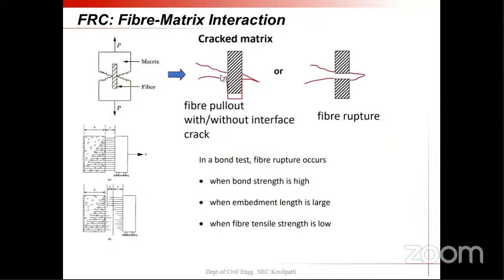So we are not going to apply 1600, because the fiber's tensile strength may vary from 1600, 1700 MPa. We are not going to apply that much stress to the concrete. So I observed most of these specimens failed only because of fiber pull-out. Fiber rupture rarely occurs, only when the bond strength is very high, when the embedment length is large, and when the fiber's tensile strength is low. But the third point is not possible. But if that is the condition, then fiber rupture may occur. So this is one point I want to mention.